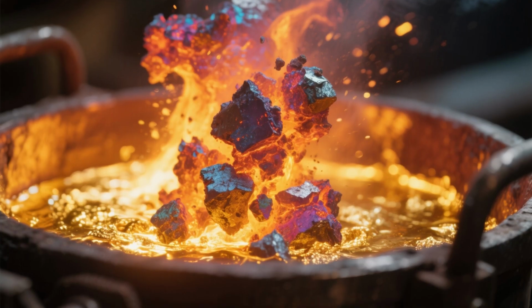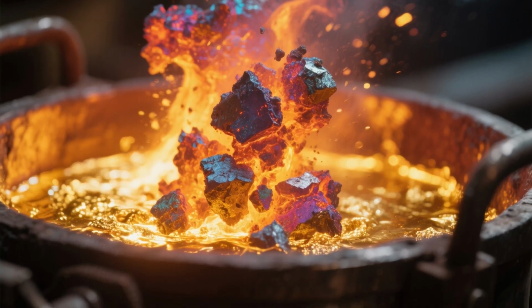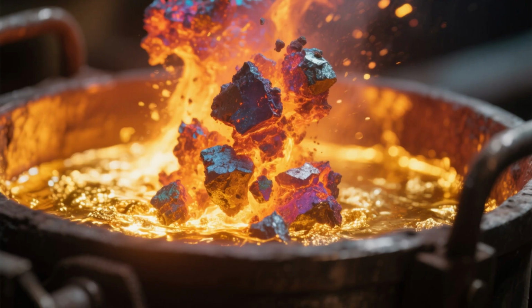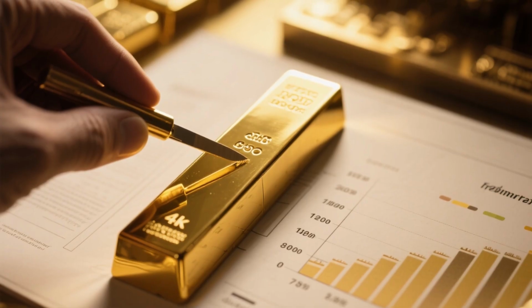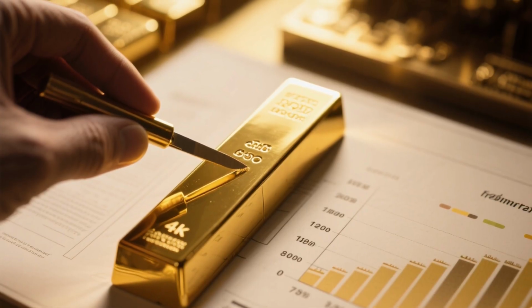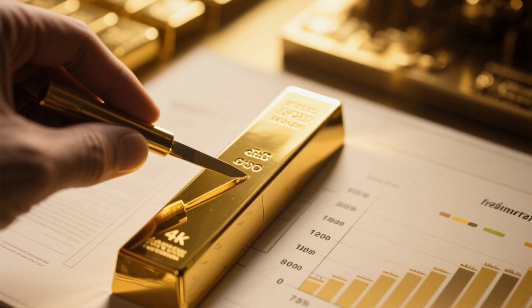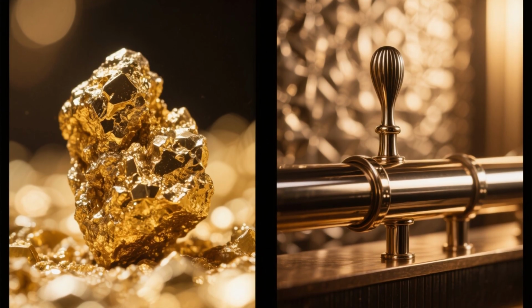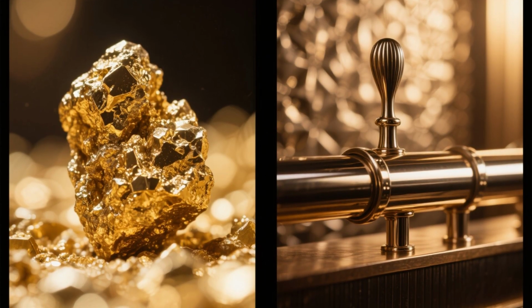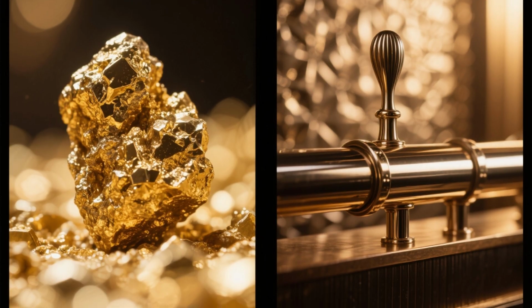Chlorine reacts with most of the remaining impurities, like base metals and silver, forming chlorides. These chlorides are less dense and rise to the surface as another layer of slag, which is then removed. This process is very effective at getting rid of silver and can produce gold that is about 99.5% pure. This is already very high-grade gold, but for financial markets and high-tech applications, we need to go even purer.